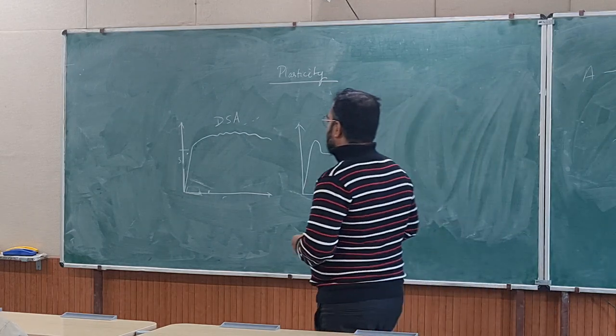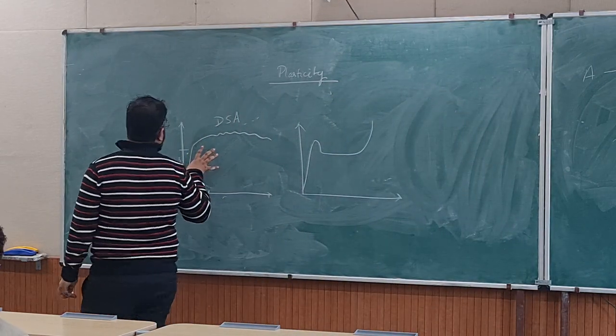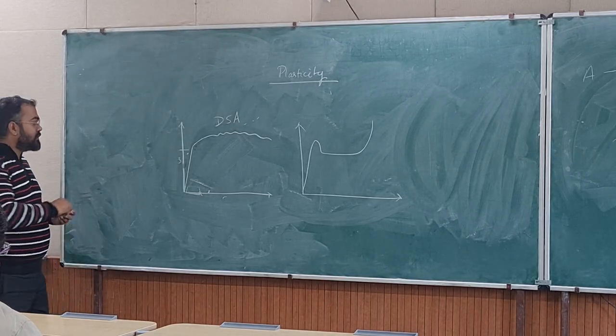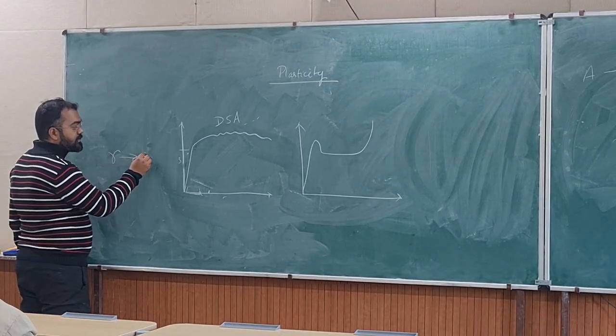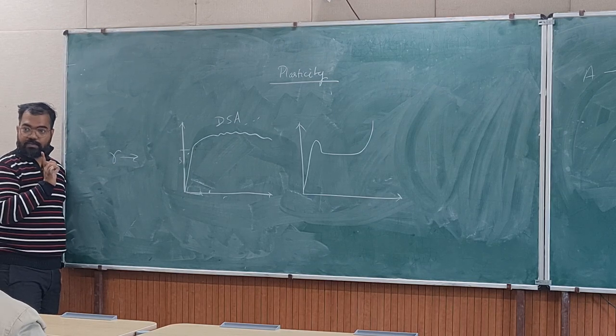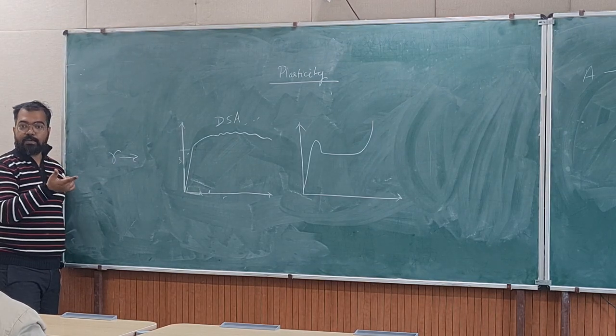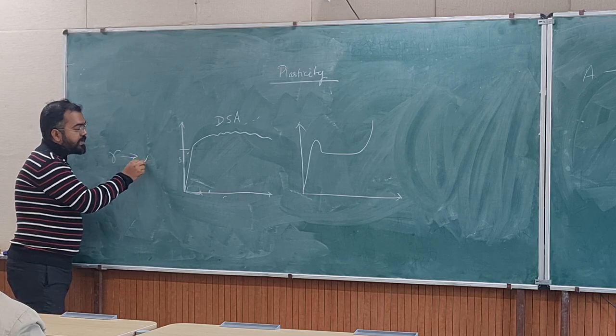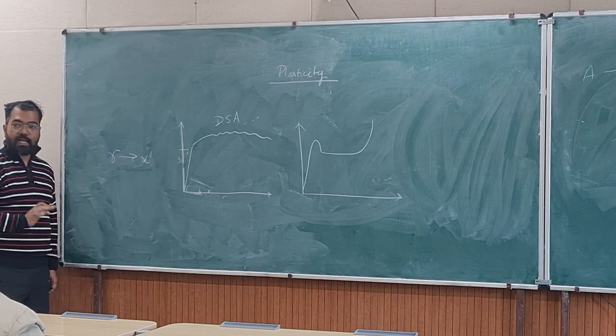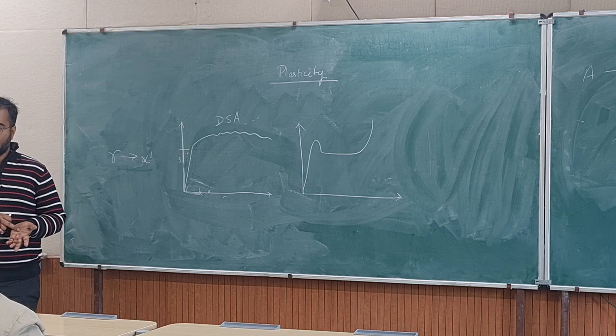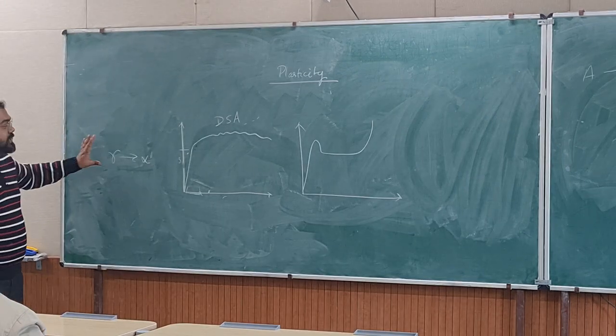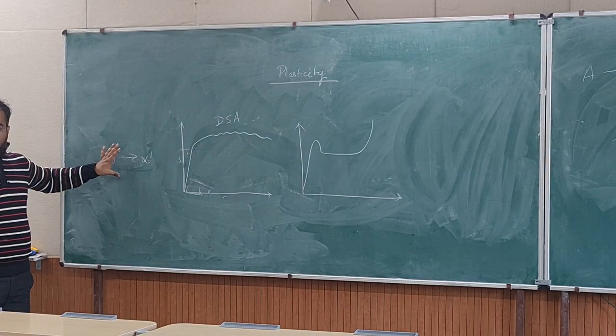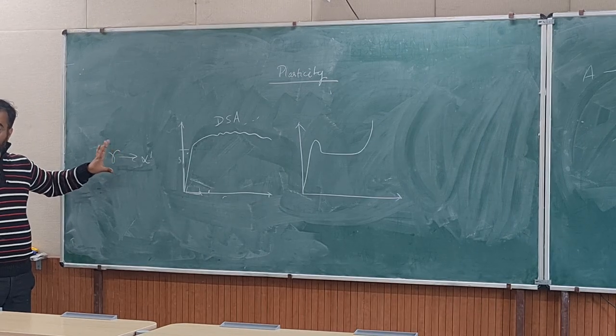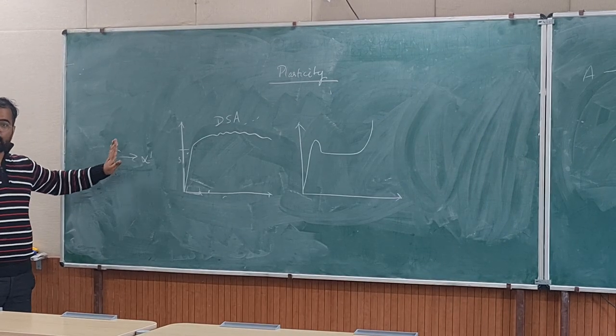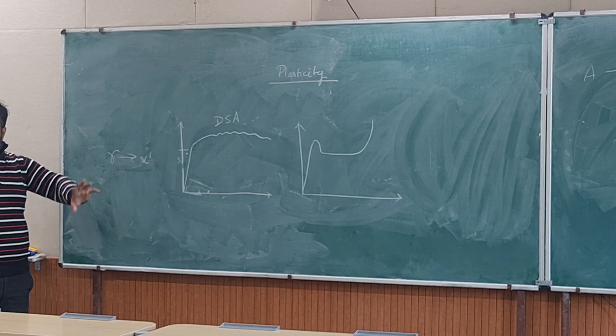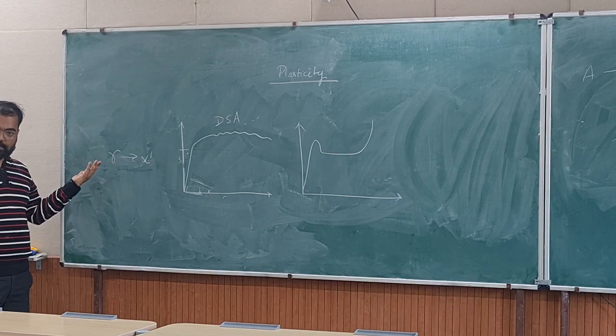So this martensite transformation phenomenon, from austenite to a phase which is not stable, which is unstable, you make it stable by non-equilibrium condition, is martensite. And this transformation can happen in many materials. And in many materials, this transformation can happen by the application of stress. If you deform it, the phase will change to martensite. If you take the load away, it will come back to austenite.